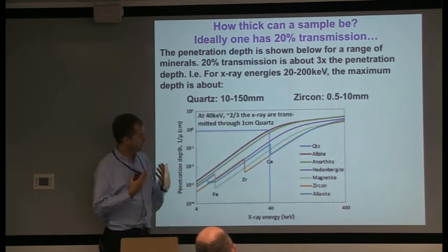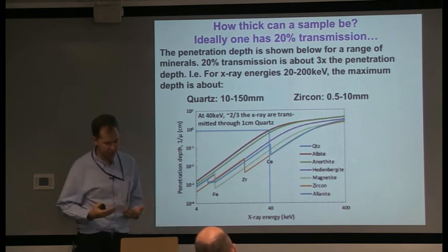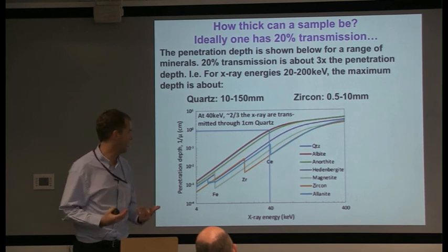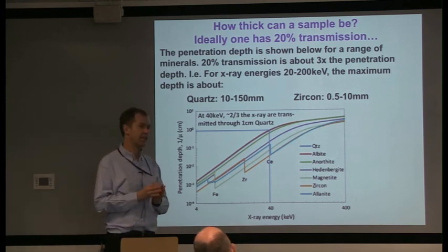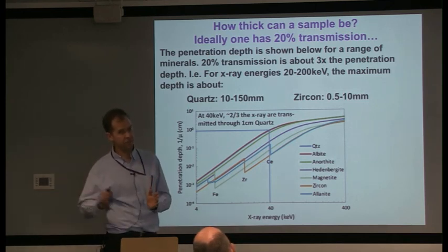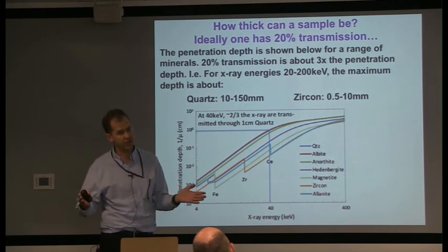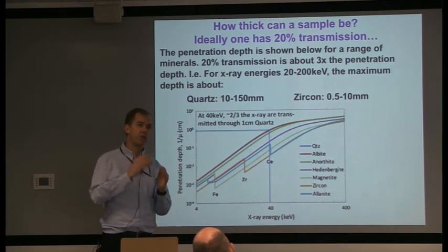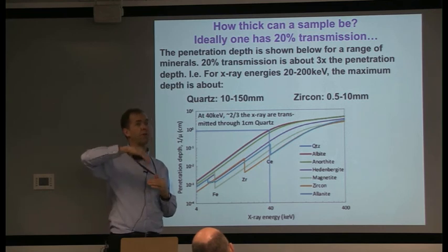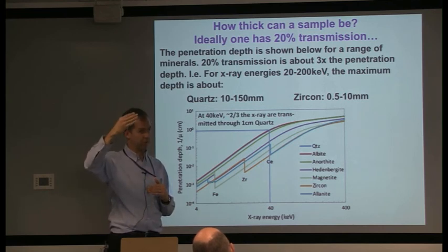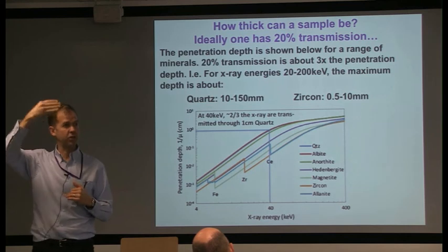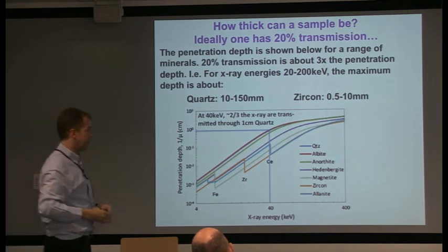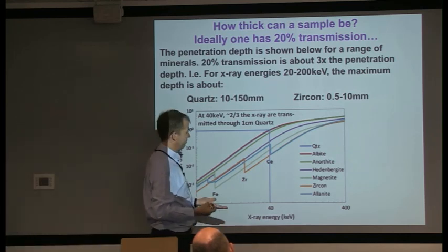Because of the energy of the electrons, basically X-ray attenuation goes with the electron density. Electron density is equal linearly to density, so if you double the density of material, it has twice as many electrons. If you go up an atomic number, it goes up with about the square of the atomic number - so if you go from an atomic number of 10 to 20, you've gone up by the square of that difference.